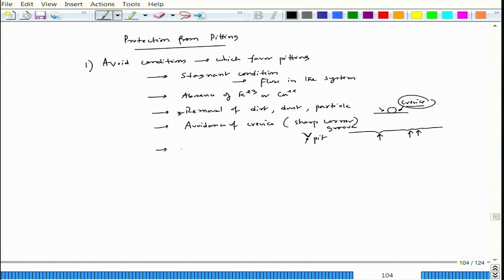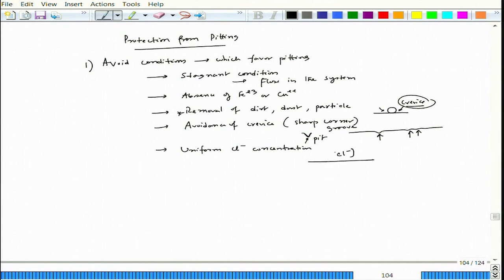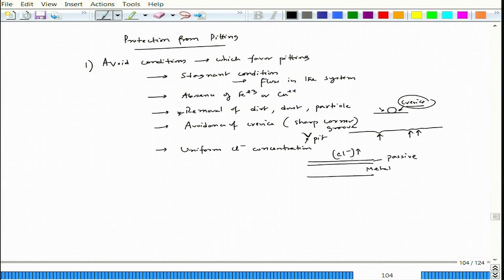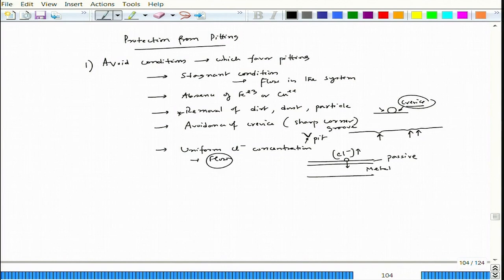Maintaining uniform chloride ion concentration is important. If locally the chloride ion concentration increases on a flat surface, it disturbs the passivity and can lead to pitting. For example, if the passive layer is disrupted by a momentary local increase in chloride concentration, a pit starts forming there and grows aggressively because the rest of the surface is protected by the anodic sacrificial effect of the pit. Uniform chloride ion concentration can only be maintained by having flow in the system.